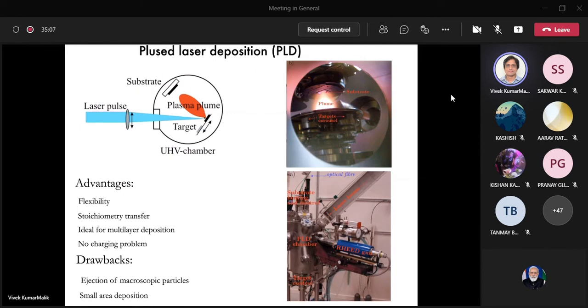a laser pulse on this target, a very high intensity laser pulse, which you focus in a small spot size. So most of the energy is concentrated on a very small spot size. So the electric field of the laser pulse is very, very high. And due to that electric field, the breakdown occurs in this polycrystalline pellet. And due to this dielectric breakdown, electrons go away, and the remaining part is the background ions sitting in the solid.